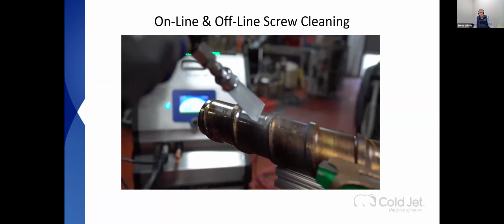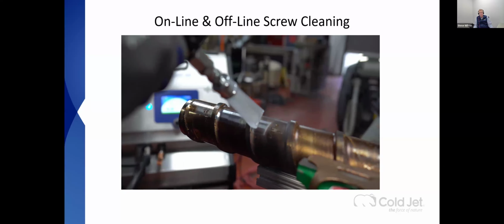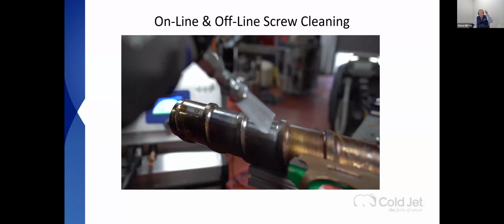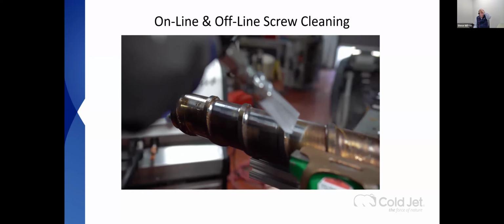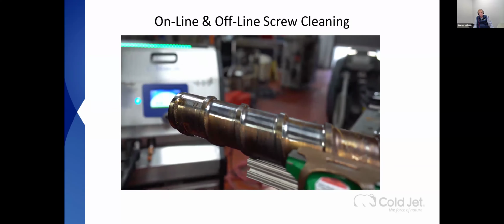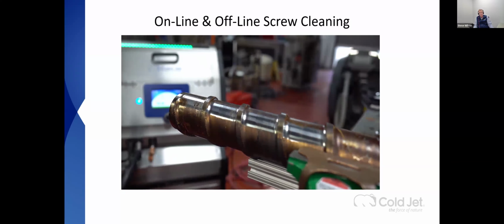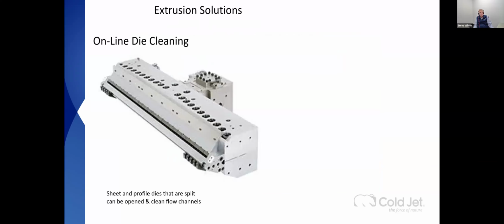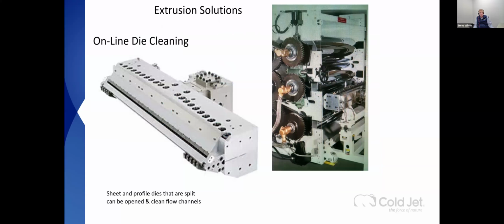They're getting away with microparticles on this one because it is a coated screw, and that's the metering section where the contaminant is pretty thin. When we got down to the transition section, it slowed down quite a bit, and we switched over to a 3 millimeter nozzle platform. Extrusion solutions: you clean dies, as long as they're split, you can open them and you can get to the flow lines.